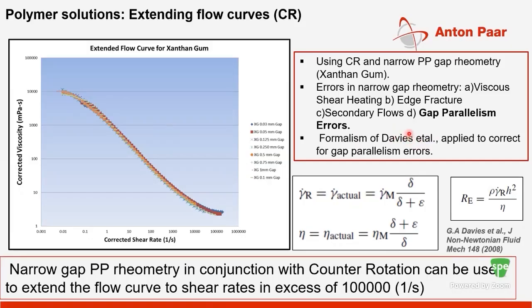The idea is to do some experiments with a Newtonian oil at different gaps and figure out what is the error in gap. Then once you have that, the results of the final sample, which is then xanthan gum in the system, is corrected with that gap error. You can see more details in this paper here. With correction of the data, I could really extend the data in excess of 100,000 inverse second, so you can clearly see the benefit of having a counter rotation type device.